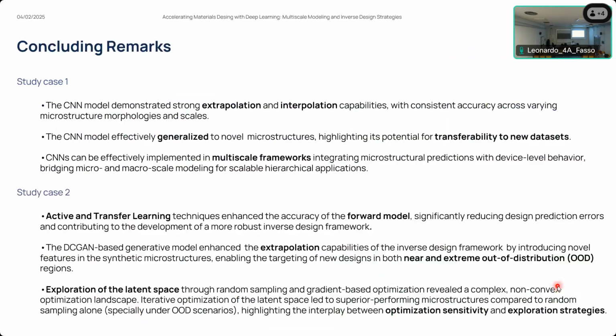So just to provide some concluding remarks regarding the 2 studies. Regarding the first study case, we see that the CNN model demonstrated strong extrapolation and interpolation capabilities with consistent accuracy across varying microstructure morphologies and scale. The CNN model was able to effectively generalize to new microstructures, which highlights the potential for transferability to new datasets. And CNNs can be effectively implemented in multiscale frameworks, integrating microstructural predictions with device-level behavior. This will bridge micro and macro scale modeling, allowing for scalable hierarchical applications.